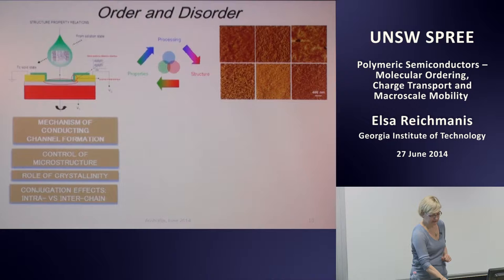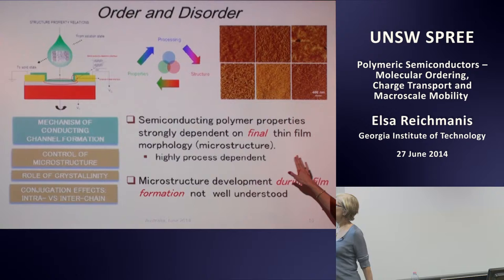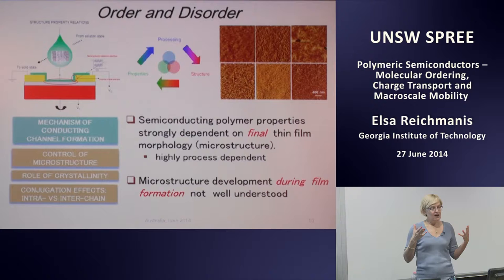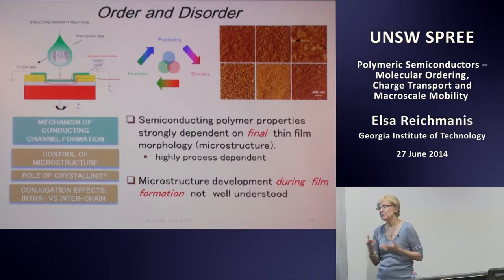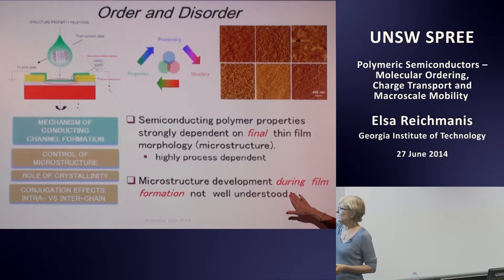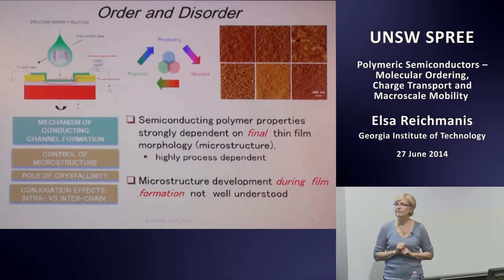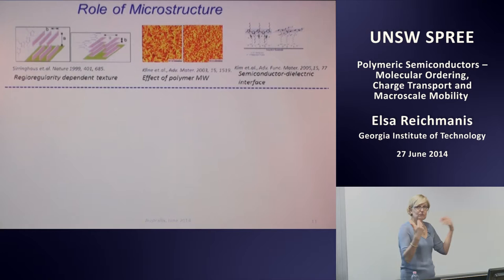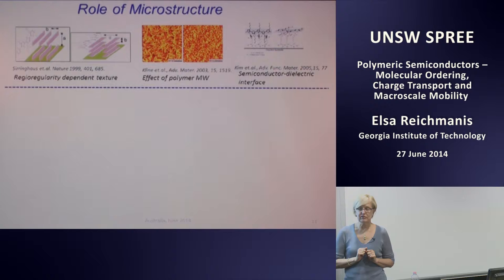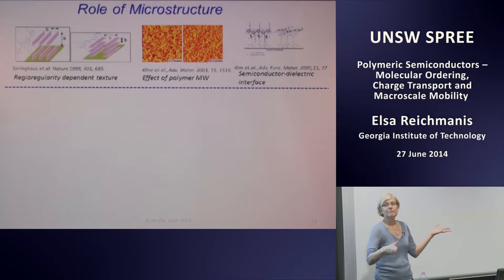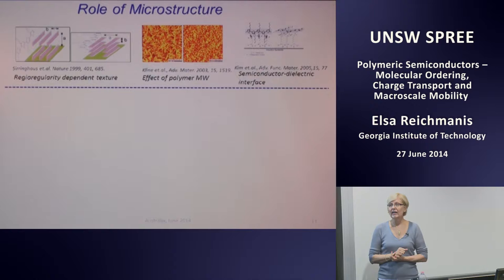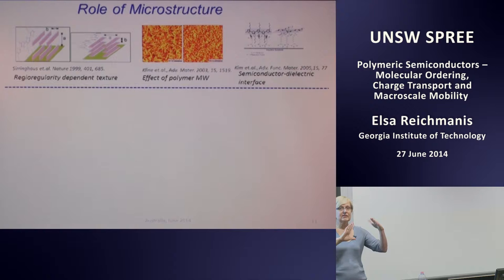All right, so that leads to wanting to have some idea of the structure, processing, and property relationships as we work on these materials. So just very briefly, the semiconductor polymer properties are really going to depend very strongly on how that morphology forms, how that material has been processed from solution. And the development of the final microstructure during film formation is not very well understood. So looking at the role of microstructure, first from what's known in the literature, certainly there were efforts by Sirringhaus early on demonstrating that regioregularity of poly-3-hexylthiophene plays an important role. And by that I mean the orientation of the hexyl side group on the polymer backbone. So how regular is this head-to-tail arrangement of the polymer?